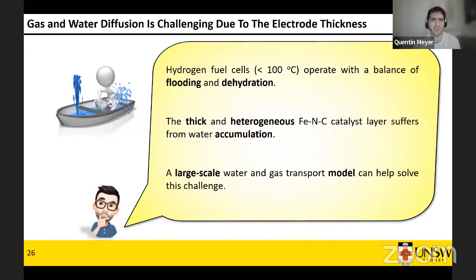Now I'm going to focus on a bit of a different challenge. So gas and water diffusion is quite challenging due to the electrode thickness. So in my case, what we had is a fuel cell that operates at low temperatures, so below 100 degrees, and it produces water. So there is a very delicate balance between flooding and dehydration. The reason it's so delicate is that the ionomer, Nafion, needs a certain amount of water to operate properly. However, if you don't remove the water that you produce in the cell, you're going to have flooding with gas diffusion problems. And if you remove too much water, if you're too efficient, you will dehydrate the cell, you'll have lower proton conductivity, and you'll have new problems again.